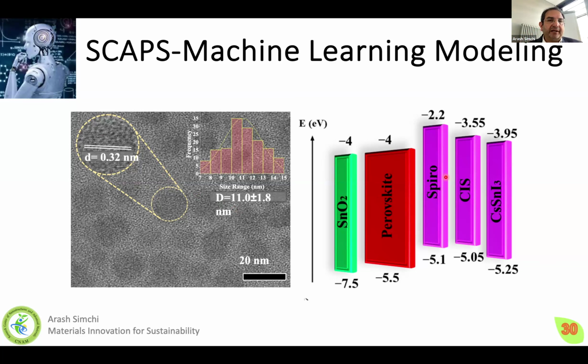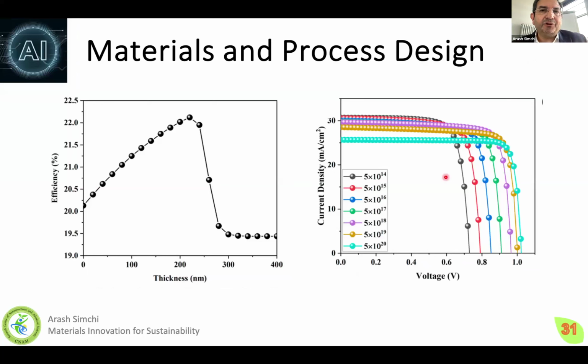What we did before in our lab, we would go to the lab and just play with the layer thickness, the doping density and so on. It's a lot of effort and a lot of cost to develop such a solar cell. What we did, for example, I would like to show you, is a combination of machine learning and SCAPS simulation. For example, we investigated efficiency versus the thickness of the perovskite layer. And we found that the efficiency can reach 22% at a thickness of 200 nanometers.